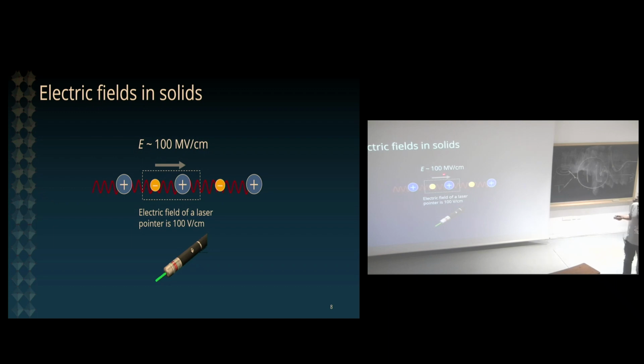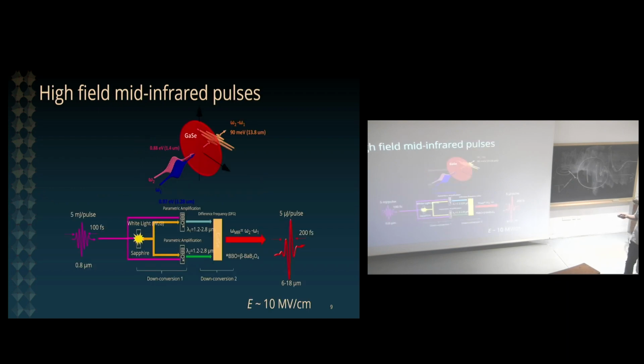So we would like ideally to have something of the order of 10% or a few percent of this to have some significant atomic motion. That's why we need to build some strong light sources, and in our lab we have chosen to generate mid-infrared pulses through a series of photon down conversions. So we start from the output of a femtosecond laser system that gives us pulses with a wavelength of 800 nanometers, photon energy 1.5 electron volts, and energy per pulse of the order of 5 millijoule. Okay. And this pulse is used to induce a series of nonlinear optical processes which convert down the photon energy to the desired range.